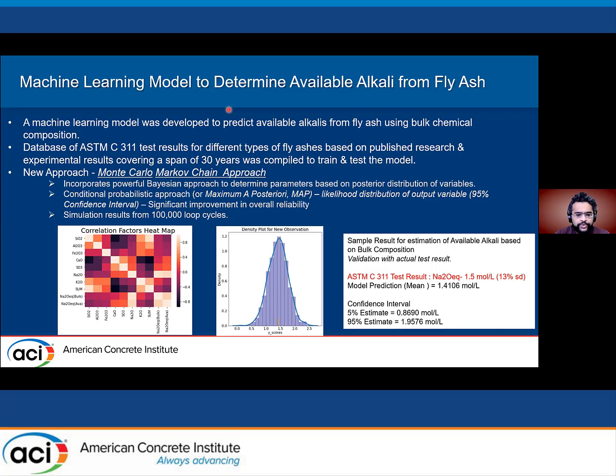And that is very important, because in extreme critical situations, your consideration has to be towards the level at the 95% confidence, or the upper threshold level, or for very moderate or low severity conditions, we could go even at 5%. So for one of the test values that we provided, the actual test result was 1.5 and the model predicted 1.4. But this consideration of the overall confidence interval, the 5 and 95%, allows us to incorporate more reliability into the overall estimation.